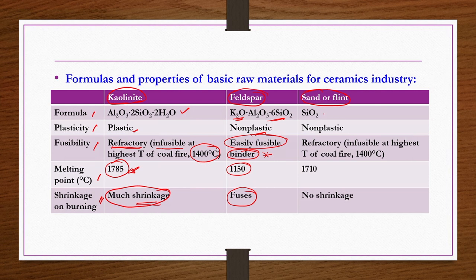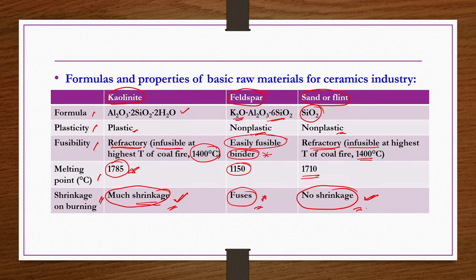Okay. The third one is sand, which is SiO2, which is non-plastic and refractory because its melting temperature is 1710 degrees centigrade, and because of that it is infusible even at 1400 degrees centigrade. But the good thing is that it does not undergo any shrinkage on burning. So now you see one material has a lot of shrinkage, another has no shrinkage, and the third undergoes fusing on burning. So three important materials have three important characteristics. Proper combination of these materials has to be taken as per the requirement of the product to make the required ceramic product. Because of their distinctive characteristics, all of them are very much essential from the ceramic products viewpoint. So that is what we have seen about raw materials.